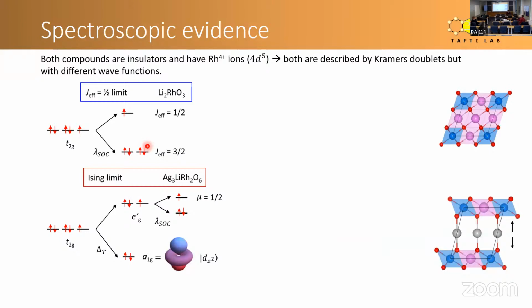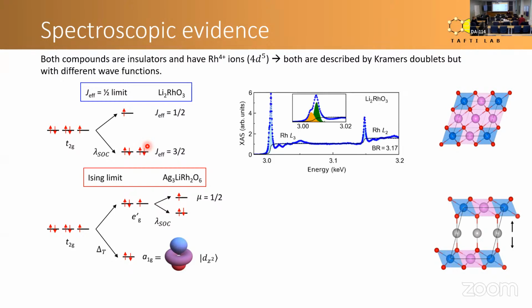Now, this was a theoretical discussion of what's happening, but there's also experimental evidence for this. The experimental evidence comes from X-ray absorption spectroscopy, something that Alberto knows much better than I. In X-ray absorption spectroscopy, you can do cool things. You can actually determine the strength of spin orbit coupling by measuring the absorption at the rhodium L3 edge and L2 edge,